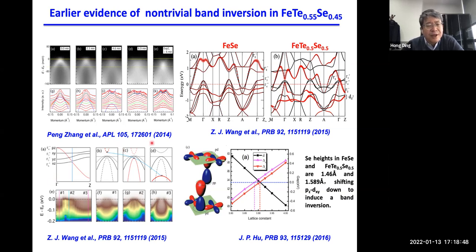We actually, back in 2014, my student did the experiment in the synchrotron in Berkeley, at the Lawrence lab, to see this whole Fermi surface. In this material it is kind of unusual. It's not a smooth parabola, but like a triangle. So he doped the surface with potassium, essentially to raise the Fermi energy to see what's happening above this triangle. It seems to show another electron-like band. But this data is quite fuzzy. We kind of argued whether this is a Dirac cone.